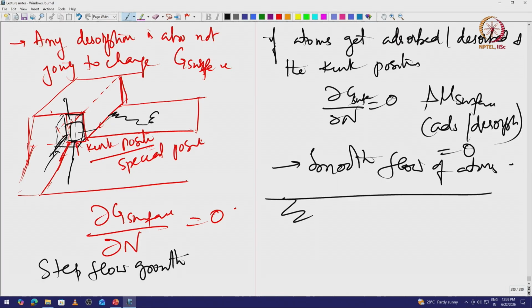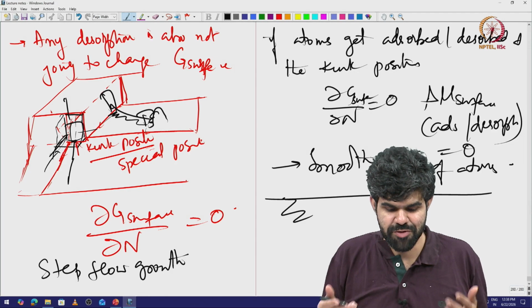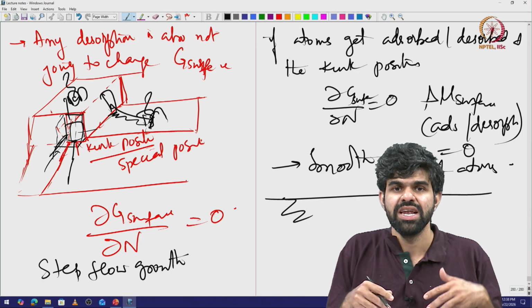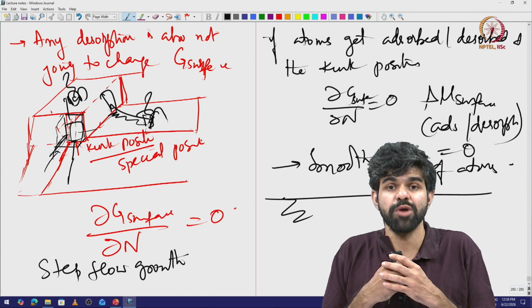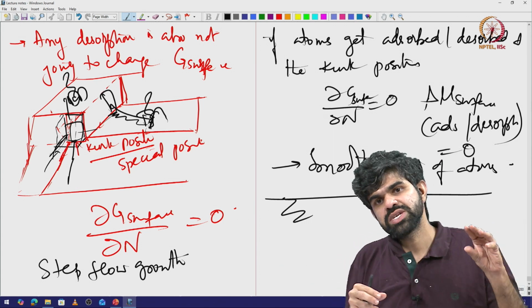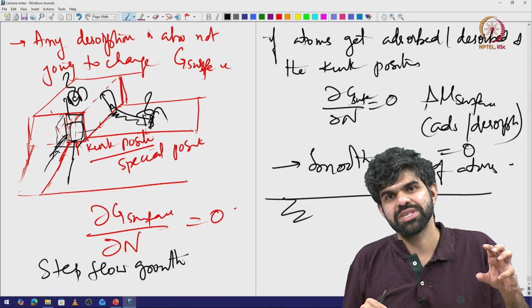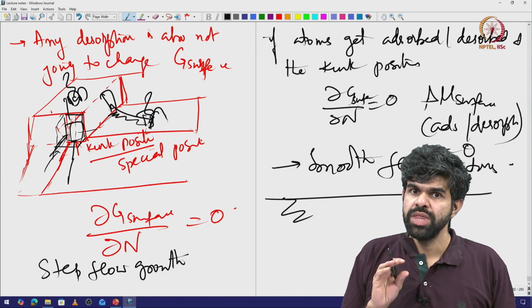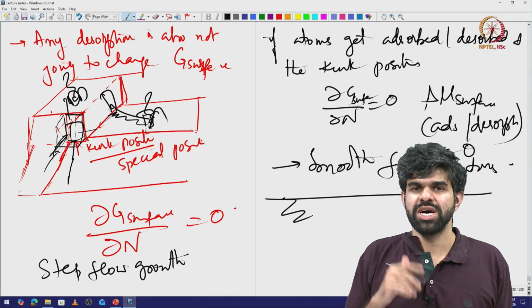So, you can sometimes have atoms coming and getting stuck here, that is also possible. Sometimes atoms can just nucleate here. I will show you more types of growth where atoms can just get nucleated here. So, it is not that site 1, site 5, all these are improbable, they are probable, right. But the nicest way of growth happens when atoms go and get stuck at the kinks.